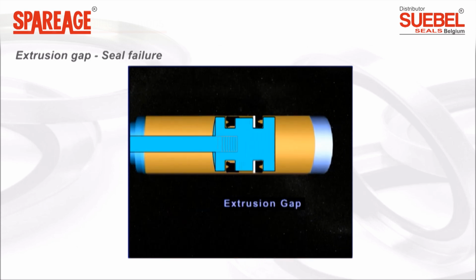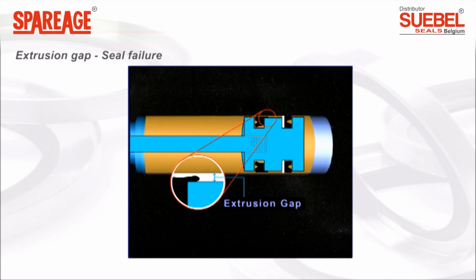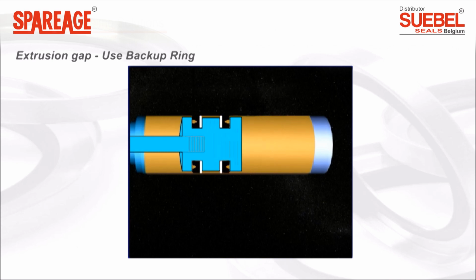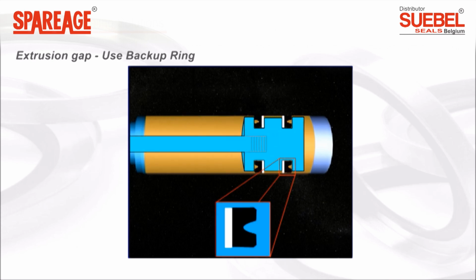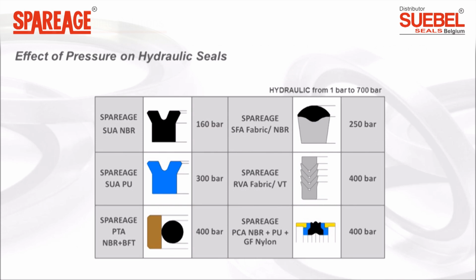Under pressure, the seal material deforms and enters into the extrusion gap, damaging the seal and resulting in premature failure. Use of backup rings or materials with higher extrusion strength in tandem with a backup ring is suggested. The Sparage SUA profile on screen is made of nitrile rubber 90 Shore A hardness, which is suitable for pressure of 160 bar.